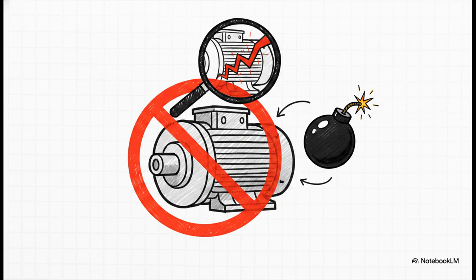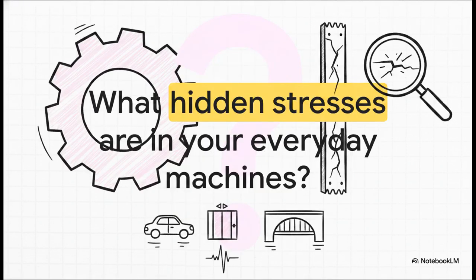So you shut it down, you run the non-destructive testing, and you find that crack before the machine violently tears itself apart. Fatigue failure is truly a master of disguise. It doesn't scream, it whispers, building up damage cycle by cycle, day by day, until the very last possible moment. But by treating machine failure as a true forensic science, engineers can read the beach marks, spot the striations, and actually outsmart this silent killer using proactive testing, which leaves us with a final thought to ponder as we wrap